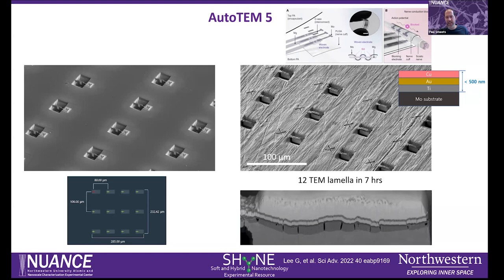This is actually a bioresorbable nerve stimulator with multi-layer metals that are present: copper, gold, titanium on a molybdenum substrate. And so I optimized the recipe for one area and made sure that the section looked good.